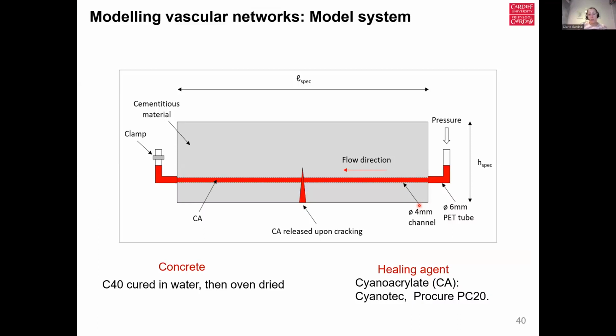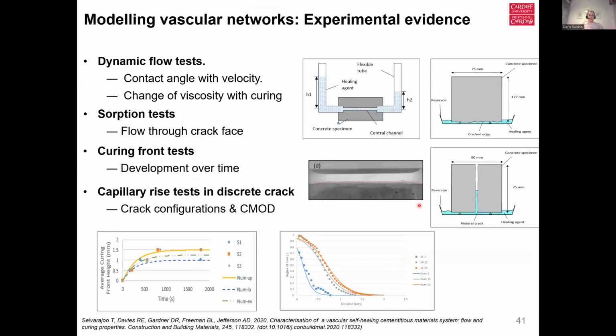And what they could do is model this system and then look at the different components that needed to feed into the model to be able to represent what we see in the lab. So first of all, there was a series of experimental evidence they needed. They needed to look at how, with respect to the healing agent in particular, how its contact angle changed with velocity as it flowed into the crack, and then the change of viscosity with curing. So as soon as a healing agent hits a cementitious matrix, actually what you see is a increase in viscosity as it starts to cure immediately.